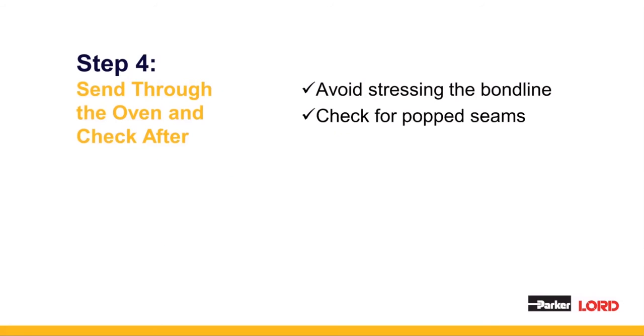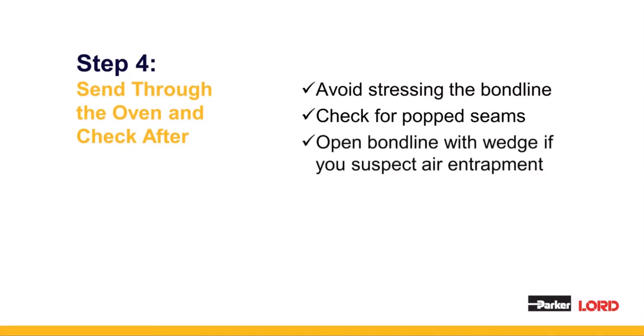After the parts come out of the oven, make sure to check your joints for any popped areas or seams. If you suspect that there was air entrapment, grab a wedge and jam it into the bond line. Put the bond line into peel and just break it apart. That way you can see what the bond line is like in between. We recommend this technique really only on test parts, as these will likely need to be scrapped afterwards. If air does become entrapped, it's best to catch it before the parts go through the oven so you can restart your bonding process and not worry about scrapping your parts.